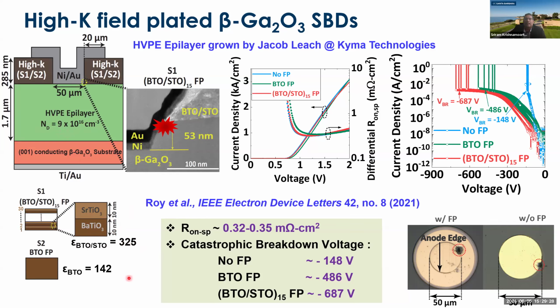And by doing this, we were able to get 600, close to 700 volt breakdown in this thin epitaxial layer without compromising the on state of the device, right? So the no field plate device and the field plate device had the exact same on state characteristics in terms of on resistance, the turn on voltage, and so on.